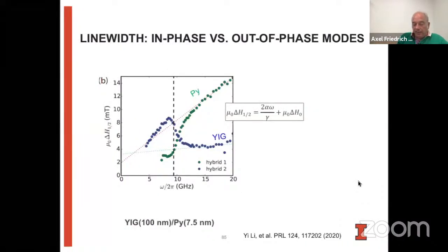One is that the crossover of the line width is actually slightly different from where the crossover of the resonance frequencies is. But more importantly, in the strong coupling regime, we see that the line width of the hybrid mode actually becomes even lower than what we would expect from the yttrium iron garnet mode alone. And for the other hybrid mode, the line width becomes larger than what you would expect from the permalloy alone. So this tells you that there is not just your normal exchange interaction, but something more complex going on, that you also have some form of dissipative coupling that changes the line width of these modes.